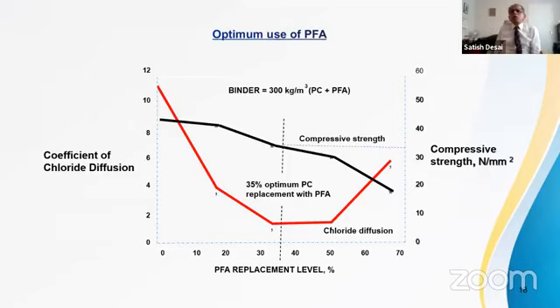Coefficient of chloride diffusion is on the left-hand y-axis. The x-axis shows PFA replacement level. The red line is dropping up to a point, which means that concrete is getting more chloride resistant. Chloride resistance is improved up to a point. On the right-hand axis is compressive strength of concrete in newtons per millimeter square, which drops a little, but a happy compromise is reached when PFA replacement level is 35%, good chloride resistance and reasonable compressive strength.